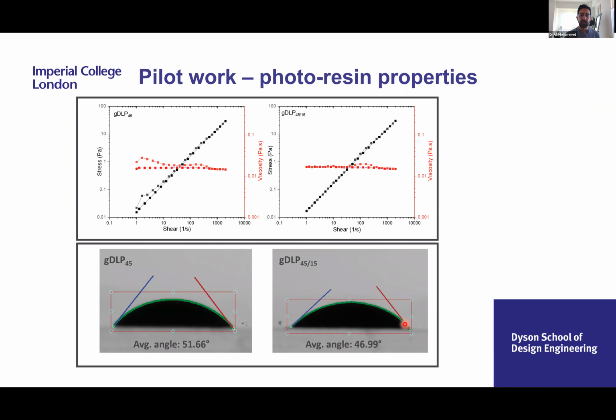Once we got to the point where we were very happy with what we had, as in a photoresin that solidified and gave us a gel, we moved forward, optimized it a little bit further, and tested the photoresin properties. Here we look at the viscosities. We wanted to ensure the resin isn't too viscous, as that will cause suction and adhesion on the build platform during printing. As we're aiming for very soft gels, this will just peel them off and cause failure of the print when the layers are lifting.